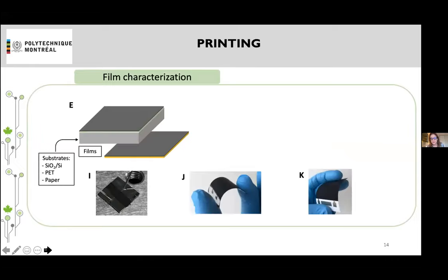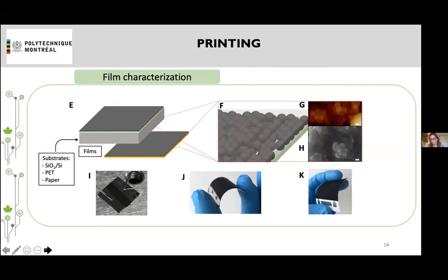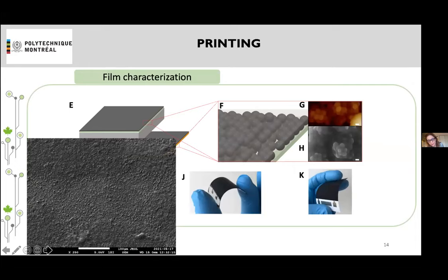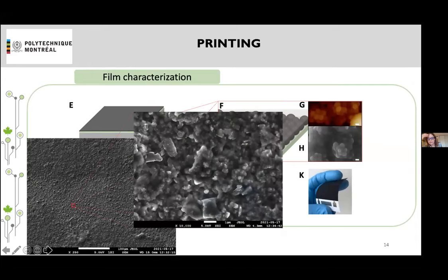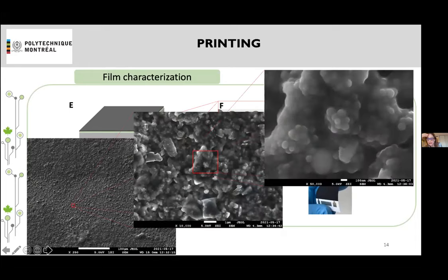We, of course, observe carefully our film at the nanoscale with scanning electron microscopy. And what we observe is something that is somehow interesting, I think. You see that you have these little spherical particles, about 100 to 200 nanometer size. These are grains of natural sepia melanin, grains that you find in the ink of the cephalopods, essentially, when they release it because they are scared, so for defense or for camouflage.